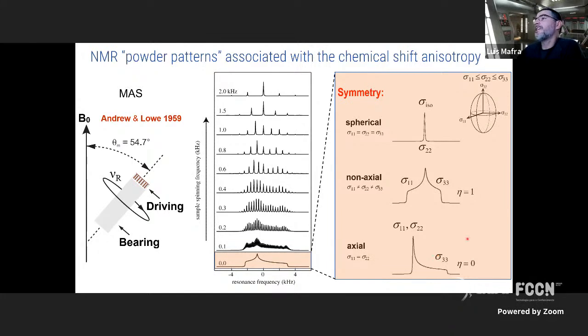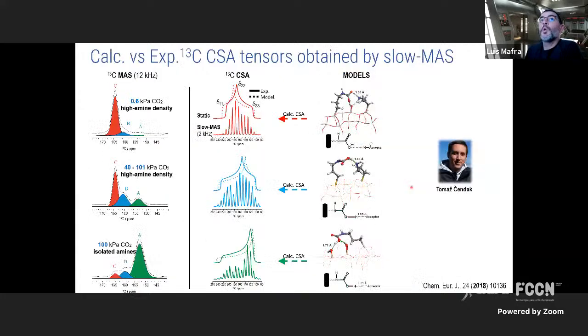But basically, these sigma 1,1, 2,2, and 3,3 are the principal components of a tensor. Interactions in NMR are defined as tensors, okay? Because of the tensorial nature of the interactions, you have these funny shapes. So we make an effort to work at particular partial pressures to favor the intensity of one of the species. If you go very low in CO2 pressure, you mostly favor the intensity of C, and then you spin the rotor very slowly on purpose, and you get a spectrum with a nice chemical shift anisotropy envelope, and you can just fit it and get the principal values of the tensor.